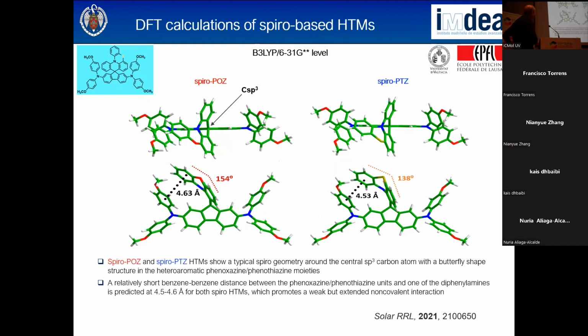So these calculations reveal the spiro nature. Here you can see an sp3 carbon atom. What is remarkable is that, in contrast to the spiro-OMeTAD, this is not planar anymore. You can see here with oxygen, and even a larger angle with the larger sulfur atom. Also remarkable is a very weak interaction, but eventually you have an electronic interaction between this ring, regardless of the oxygen or sulfur containing systems.